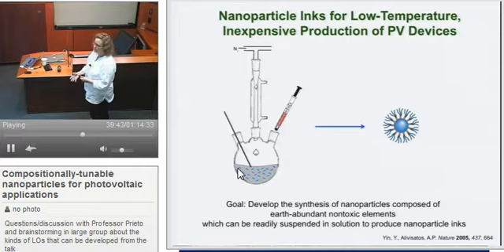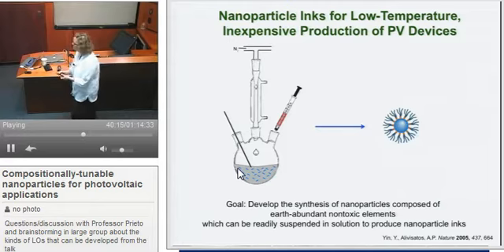And so the idea is that you can suspend these in nonpolar solvents, and then to work up these reactions, what we do is we basically take our mix here, put it into something like hexanes or toluene, and then we crash our particles out with something like methanol, and then we resuspend them, and in that way we rinse away the excess surfactant. So we do have a workup process that's very similar to, I think, molecular systems. But the idea is that we need to figure out what precursors to use, what temperature to use, and what mix of surfactants to use to make the compound that we want.